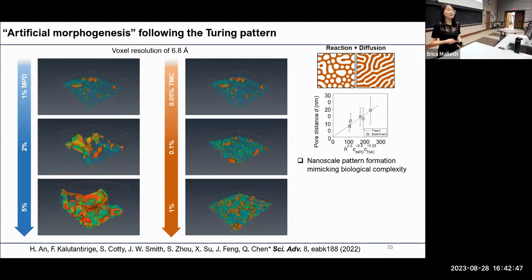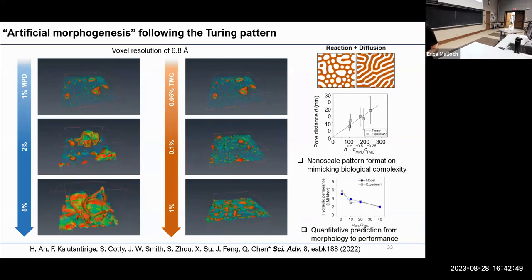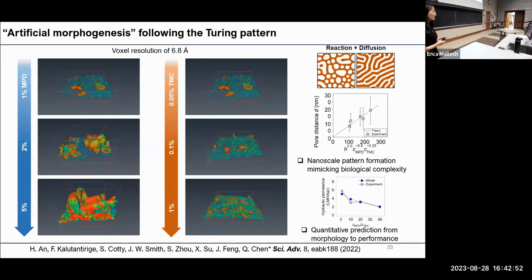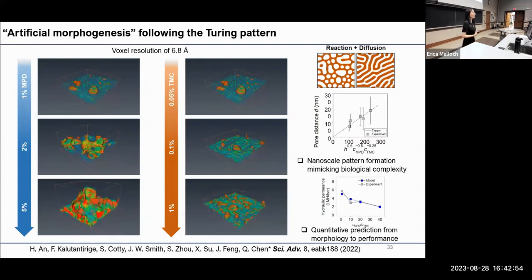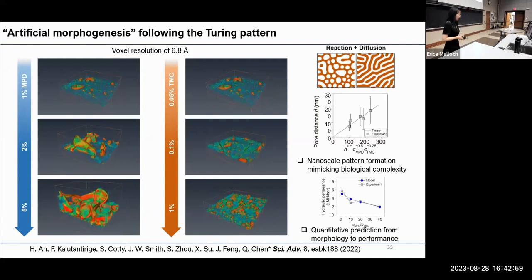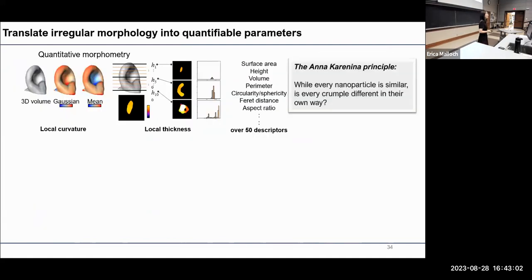And next, we're also able to measure local thickness very accurately in the presence of voids. That's how we can use those morphology parameters as input to accurately predict the molecular separation performance of the membrane. We have crumples in the membrane, and the crumples have arbitrary 3-dimensional shape. So in our effort to translate those arbitrary 3-dimensional shapes into quantifiable numbers, here we have more than 50 descriptors to detail the shape, such as 3-dimensional volume, the surface area, the height, the surface curvature.